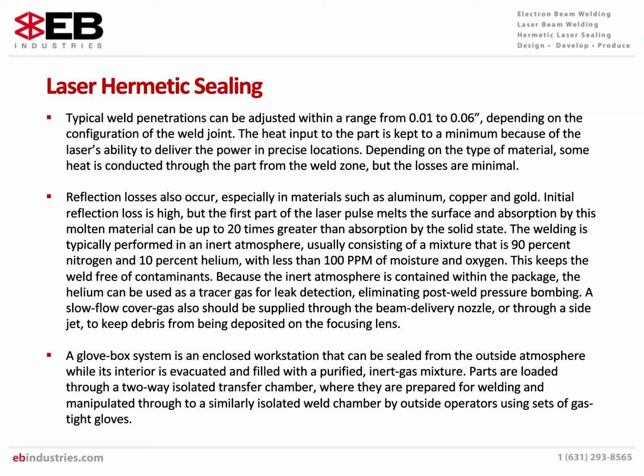Reflection losses also occur, especially in materials such as aluminum, copper, and gold. Initial reflection loss is high, but the first part of the laser pulse melts the surface, and absorption by this molten material can be up to 20 times greater than absorption by the solid state. The welding is typically performed in an inert atmosphere, usually consisting of a mixture that is 90% nitrogen and 10% helium with less than 100 parts per million of moisture and oxygen. This keeps the weld free of contaminants.